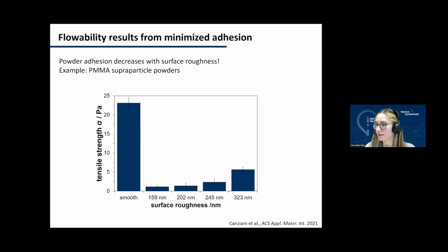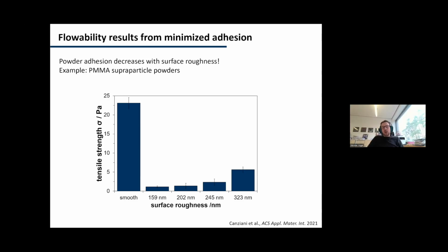Perfect, thank you. So I have one other question. In what quantities can you produce supraparticles? Yeah, that depends on what I said in the beginning. If you want to make them very precise and use microfluidics, then in homeopathic quantities, so you create some amount of powder, but it's more in the milligram range. If we use spray drying, then it depends on how big your spray dryer is. It's an inherently very scalable process. And then what we currently do is grams, hundreds of gram scale, so enough for tests of 3D printing and so on. But it's a matter of scaling the entire synthesis process. In this case, I would say the spray drying is not a limiting factor, but the availability of the primary particles.